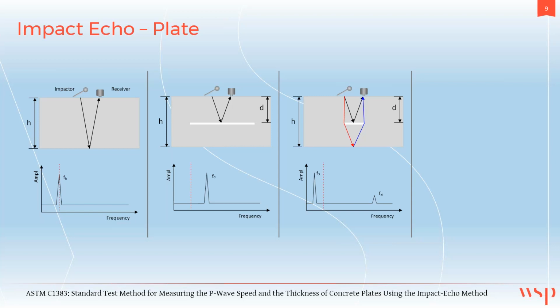So still you see a higher frequency for the shallow defect, but you also see another frequency response that is lower frequency than the fundamental thickness. And the lowering of that frequency is because the wave path travels farther to go around the relatively small defect than it would as if it were a straight path.